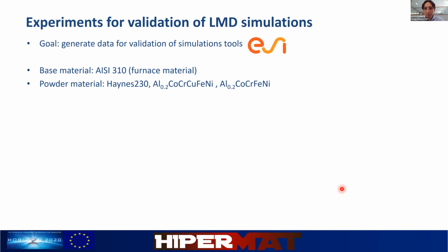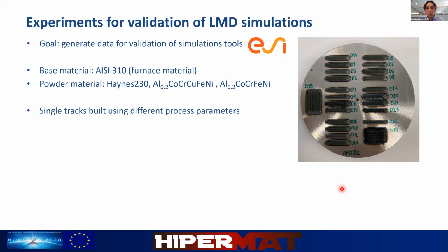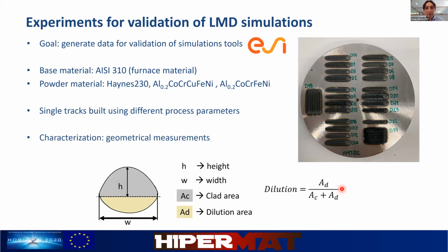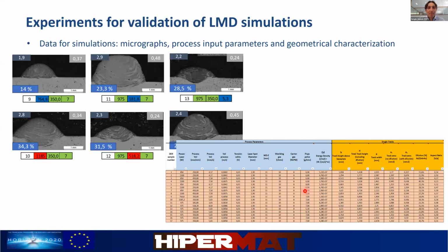Haynes 230, which is a nickel-based alloy, and 2 high entropy alloys. Both are similar. The only difference is that one of them has copper and the other hasn't. We have built several single tracks in 2 different designs of experiments. And we have characterized the main geometrical measurements using an optical microscope. For example, the height, width, clad area, the dilution area, and the dilution percentage.